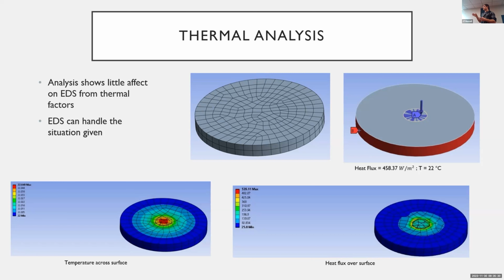Then the heat flux being applied on the top is marked in A, and the temperature is B. At the bottom left, we have the temperature across the surface. If you look closely at the top left of that image, we only have less than 0.1 of a degree Celsius change, which is really low, and that's very good. It shows that our EDS is capable of handling the voltage that we are putting into it, and able to do what we want it to do.